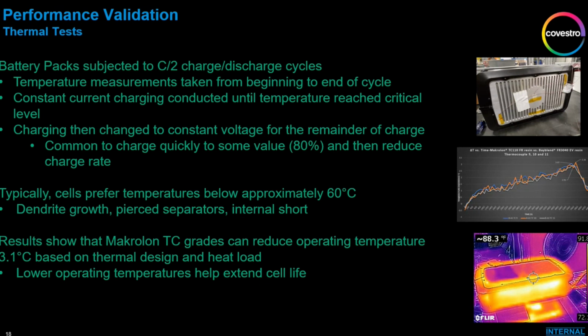So the other performance is the thermal performance of the pack, and that's also critical. And what we did in this case was wire up packs with live cells. These were Samsung cells. We ran charge and discharge cycles. We ran 1C and C/2 charge and discharge cycles. We wired up the packs with 46 thermocouples. There were 45 live thermocouples and then 1 thermocouple reading ambient. And we went through all of the data looking for how the 2 materials, a thermally conductive and a non-thermally conductive material, performed and if we saw any benefit.